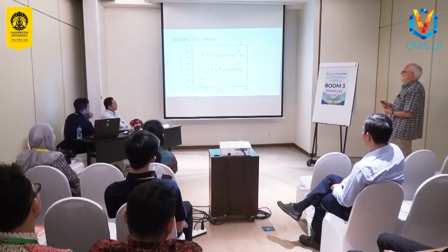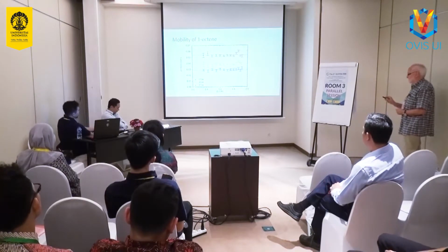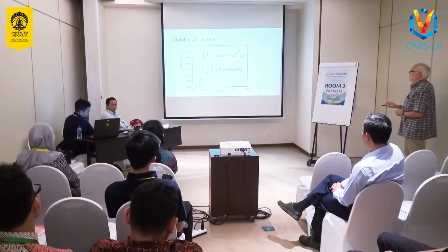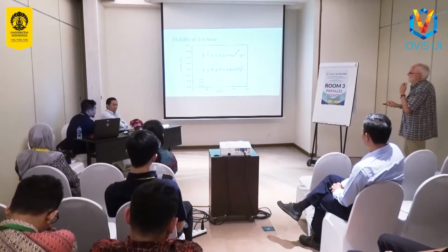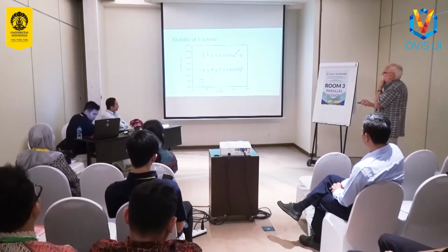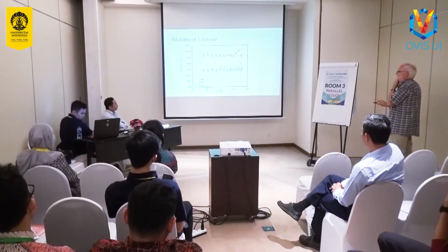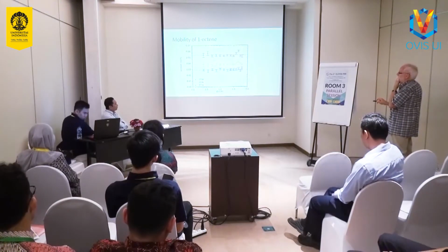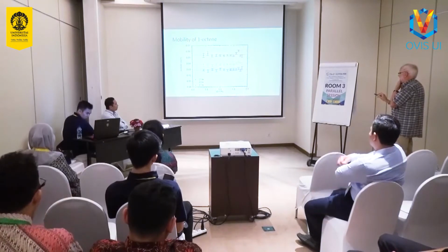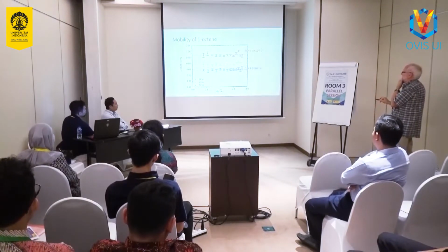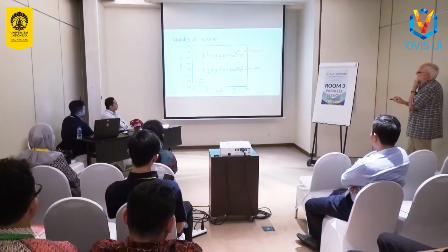We did quasielastic experiments as well to see about the mobility of the 1-octene. Here's the half-width quasielastic line as a function of Q at different temperatures. It gets broader as the temperature goes up, as you'd expect. And we could deduce diffusion coefficients from that data.